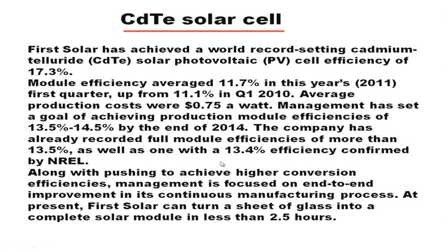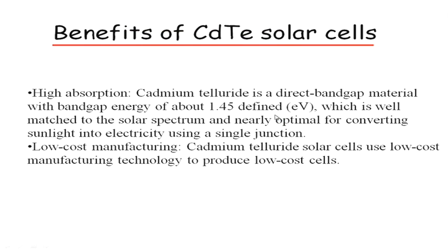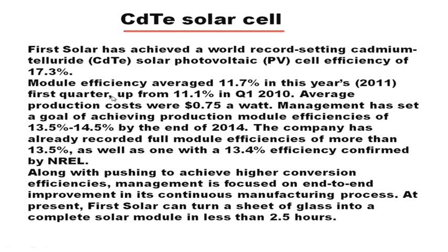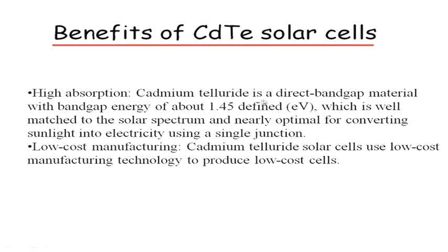Different types of structures can be made, and we shall show you. It has high absorption, and cadmium telluride is a direct band gap material with a band gap energy of about 1.45 electron volt, which is well matched to the solar spectrum and nearly optimal for converting sunlight into electricity using a single junction. And low manufacturing cost, why? Because cadmium telluride solar cells use low cost manufacturing technology. It is a thin film technology, and no bulk crystal growth is involved.